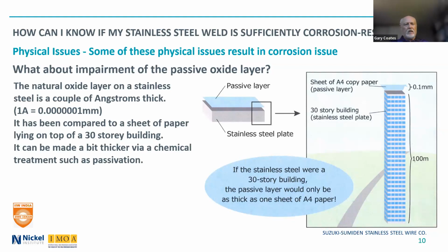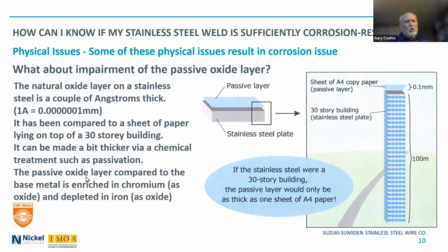It can be made a little thicker by a chemical treatment, such as passivation, but it is very, very thin, and therefore it is subject to damage. Why is the passive layer important? Well, because it is enriched in chromium as an oxide compared to the parent material, the base material, and it's depleted in iron, so lower iron content. So it actually has, let's say, a higher corrosion resistance than the base material itself.